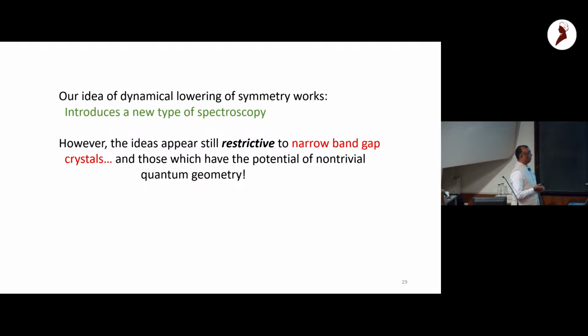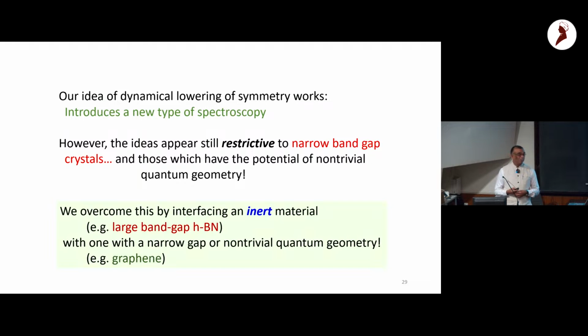As a result, we can use these ideas only for crystals which have non-trivial quantum geometry. So it's still very restrictive, and many of you would be disappointed. Look, we work on these very interesting semiconductors or other oxides which don't have this quantum geometry. So we overcome that problem by showing that you can interface your inert material, with boring quantum geometry, for example hexagonal boron nitride. I think someone asked me earlier. You interface it with graphene. Graphene, I explained to you, has some potential quantum geometry. You can combine the merits of both of them. So you can measure the frequency of HBN by using the quantum geometry of graphene, which is the substrate.